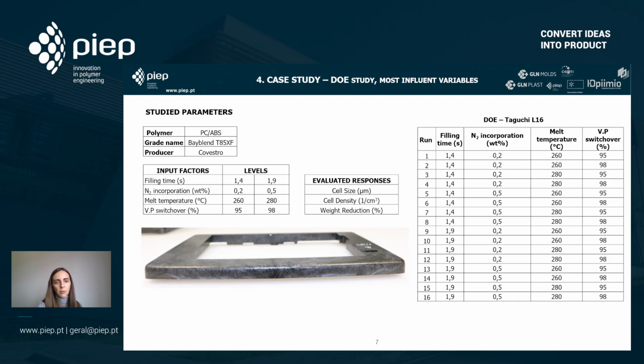So we wanted to have a 95% fill or a 98% fill of the cavity before finishing the filling of the part. Once again, the evaluated responses were cell size, cell density, and weight reduction. In this case, weight reduction is the most important. However, we have to analyze also cell size and cell density because we want to make sure that the cell structure is good for the produced part and to promote good mechanical properties.